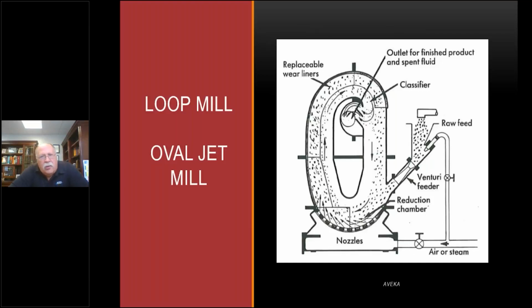So this is a schematic of an oval jet where particles are coming in from the right side here. Your raw feed is coming in. You have some high pressure air nozzles at the bottom, and this is basically a cyclonic action where the particles are being pushed around the system. They come down to the grinding zone at the bottom where the nozzles are. The particles bounce off each other and off the walls. They break up, and as the particles get smaller, the air cycles around just like a cyclone, and eventually the fine particles can leave the system. Now, with a pancake mill and an oval jet system, because the classifier is inherent to the system, you have some problem controlling the particle size distribution, and you end up with less control than you would have on a fluidized bed jet mill.